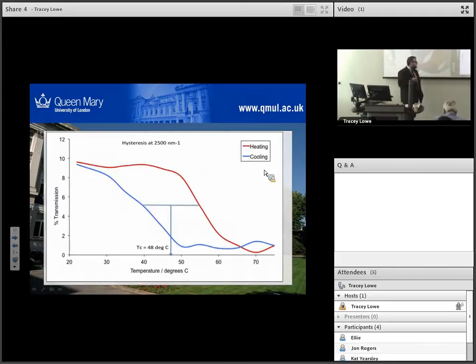So let's look at some slightly larger ones. In this case we can see there's some cycling behaviour - we've got a reduction in our transition temperature, although nowhere near where we would like it to be, and our gradient is still much wider than we'd like.